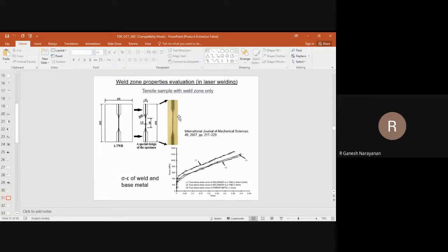Now, another important problem. Suppose you make tailor welded blanks using laser weld, and you also know that the laser weld is going to generate a weld zone which is very, very small. So sheet properties you can get from tensile test, correct? How do you get weld zone properties? Because its width is very small. There are some strategies available. I am not showing any example for modeling, but I will tell you the significance. When you do modeling, you have to give input for weld zone properties, the entire stress strain behavior. So how do you get weld zone properties?